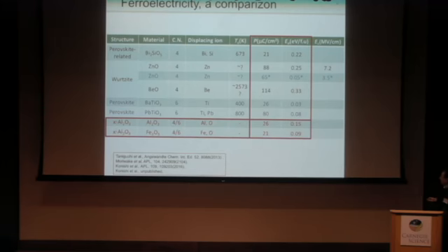And I will just show you the result of the polarization of the kappa-alumina type structure, for kappa-alumina type alumina and kappa-alumina type iron oxide. The polarization value is 21 to 26. And the most important point is that the polarization switching energy is comparable to that of the perovskite, as I mentioned before.